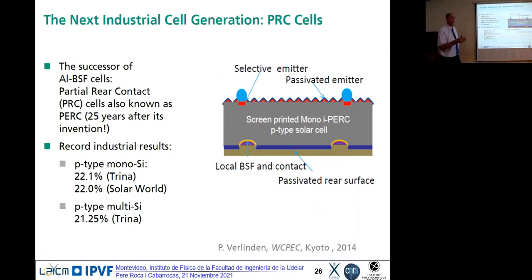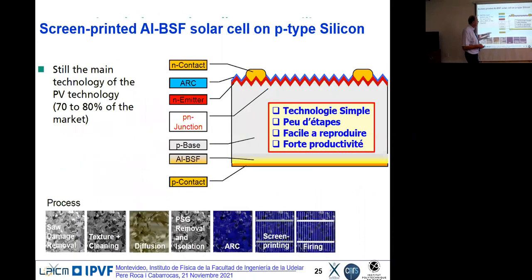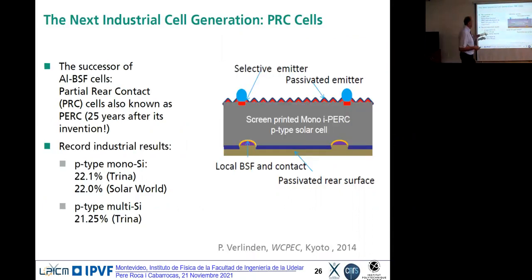It took 25 years to bring it to industrial scale, because this aluminum BSF is wonderful, but the efficiency is limited to 20%, because even with aluminum in the back you still have recombination, so you have losses. If you want to reduce that, you have to passivate. You put in a material which reduces the recombination, and you have local contacts. You open the contacts on the back locally with a laser, so you reduce the surface where recombination can happen, which means losses of current, voltage and fill factor. This is the passivated emitter rear contact.